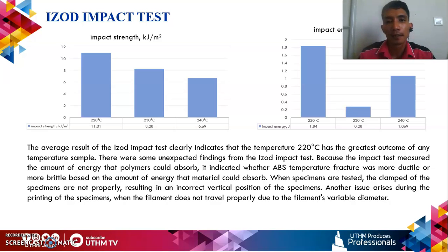Next, as we can see, the result for the Izod impact test. The left is for the impact strength, and the right is for impact energy. They also have three types of temperature, and the average result of the Izod impact test clearly indicates that 220 Celsius has the greatest outcome of any temperature sample. There were some unexpected findings from the Izod impact test, because the impact test measured the amount of energy that polymers could absorb. It indicates whether ABS fracture at a given temperature was more ductile or more brittle based on the amount of energy that the material could absorb.